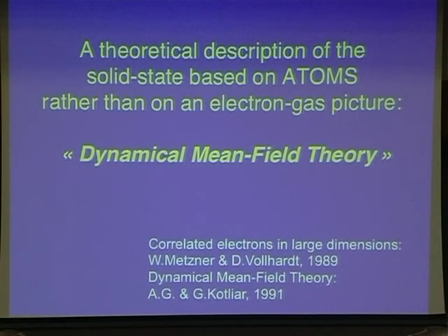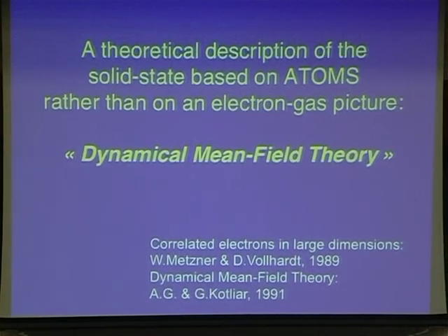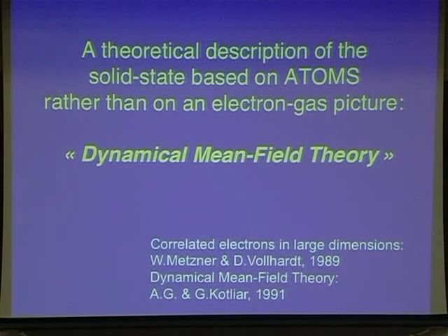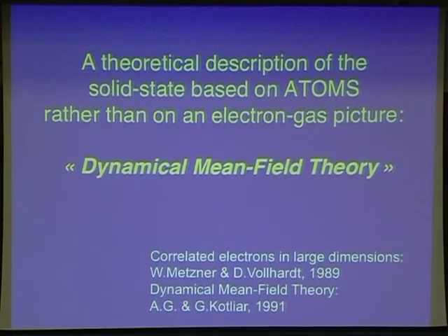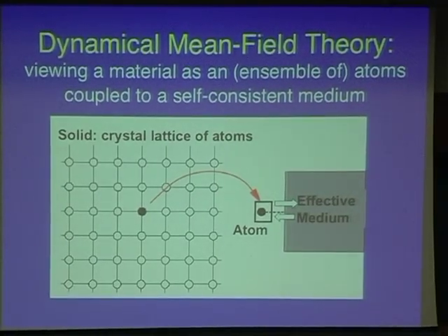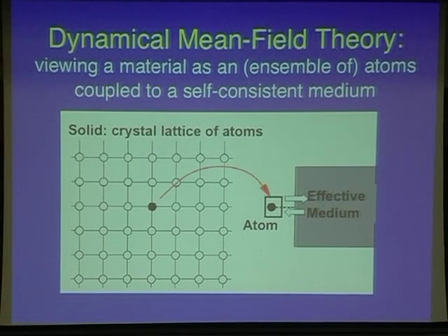So this is precisely what this theory, which was referred to in several instances previously in the school and in the talks this morning, but not yet really explained, has aimed at doing. This so-called dynamical mean field theory emerged initially as attention paid to the limit of the Hubbard model in large dimensionalities, which eventually resulted in the construction of a mean field theory of the strongly correlated system that Gabi Kotliar and myself elaborated in the early 90s, and which is now known as dynamical mean field theory. I will devote lecture 2 of the Chandrasekhar lectures to briefly introduce this theory and especially give you some overview of the most recent results that have been obtained with this theory.